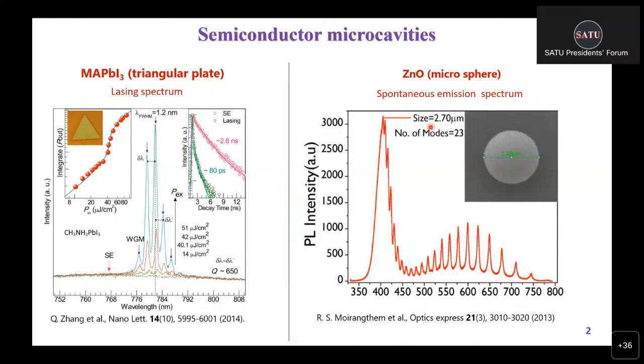On the right-hand side, the microstructure is a zinc oxide microsphere. We still observe many optical modes in the spectrum. However, these are not lasing action. These are spontaneous emission. The sharp optical modes are because of the enhancement of the recombination rate by the Purcell effect, due to the high degree of symmetry of this microsphere.